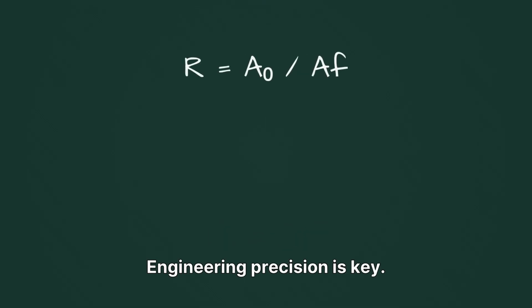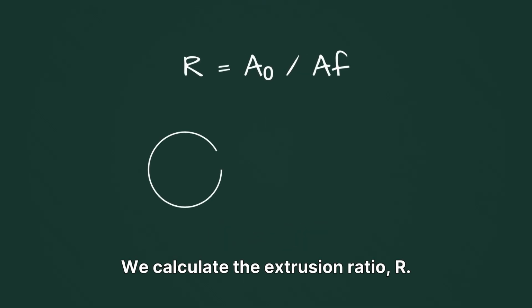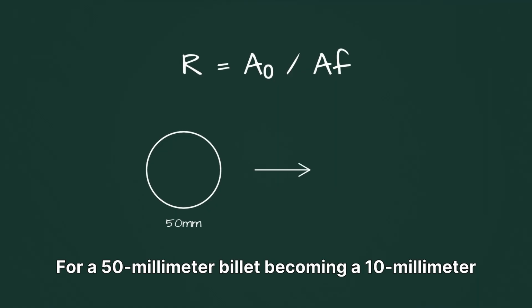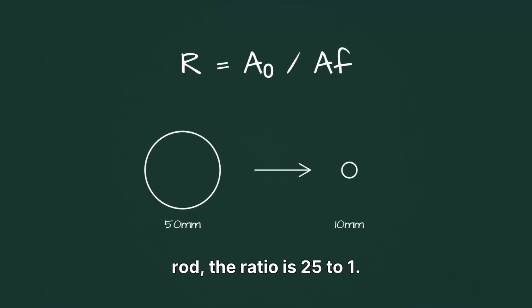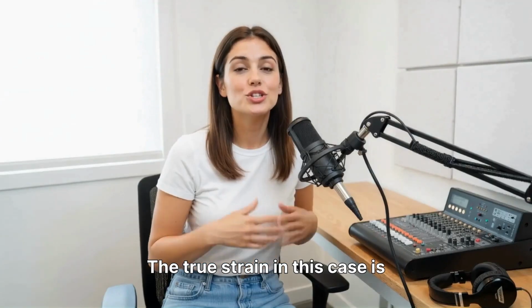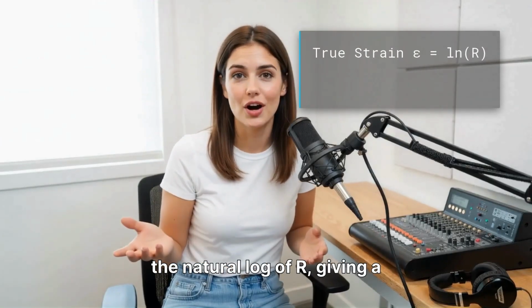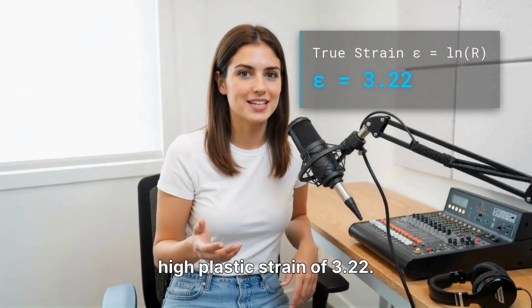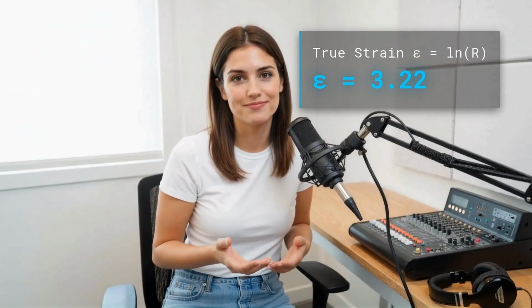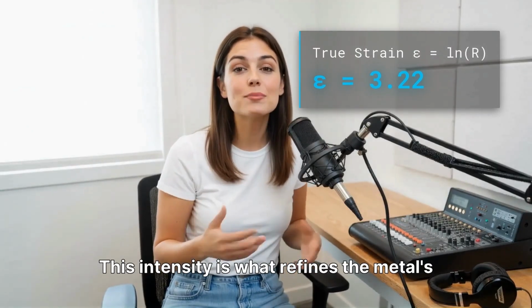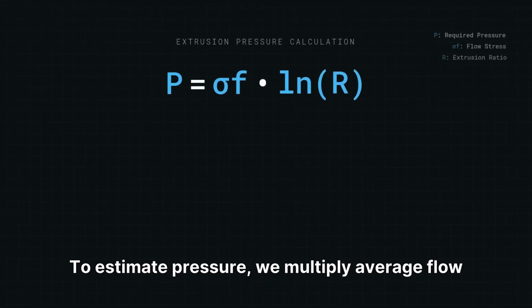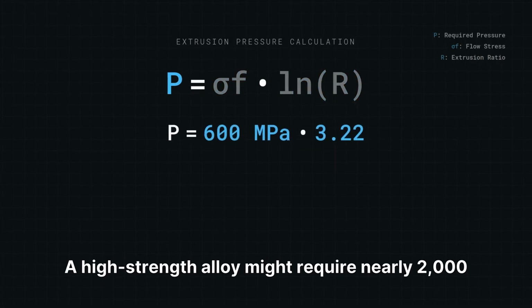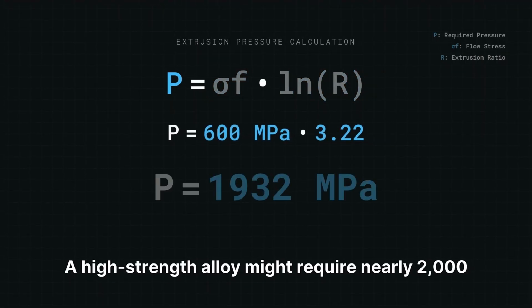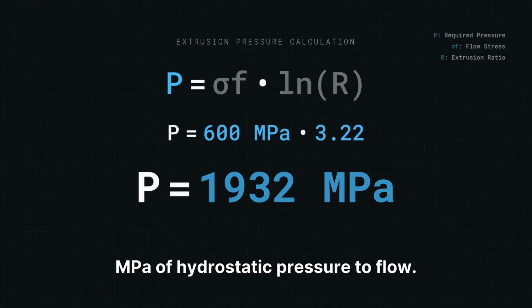Engineering precision is key. We calculate the extrusion ratio, R. For a 50mm billet becoming a 10mm rod, the ratio is 25:1. The true strain in this case is the natural log of R, giving a high plastic strain of 3.22. This intensity is what refines the metal's grain structure. To estimate pressure, we multiply average flow stress by the strain. A high-strength alloy might require nearly 2,000 megapascals of hydrostatic pressure to flow.